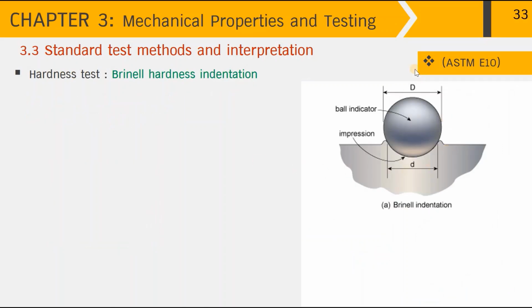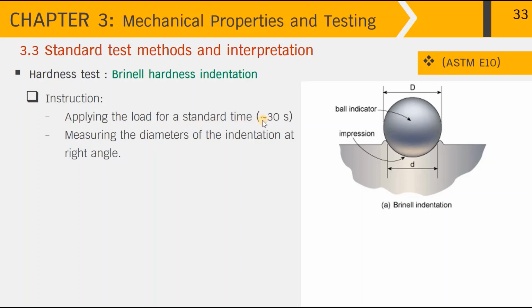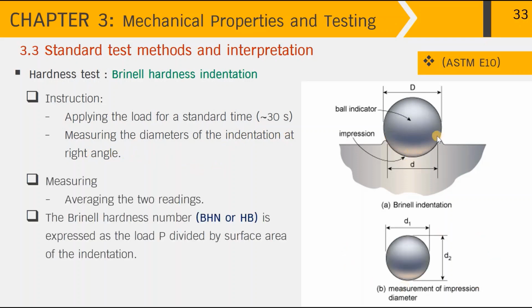To measure the impression, have a look at the cross-section here. The steel ball indenter has a diameter of capital D, and once it makes the impression on the metal surface, we have an impression of diameter small d. After applying the load for a standard time of about 30 seconds, we measure the diameters of the indentation at right angles, as you can see here. The impression has 2 diameters normal to each other, D1 and D2. The average of these 2 readings gives the measurement for the Brinell hardness number.